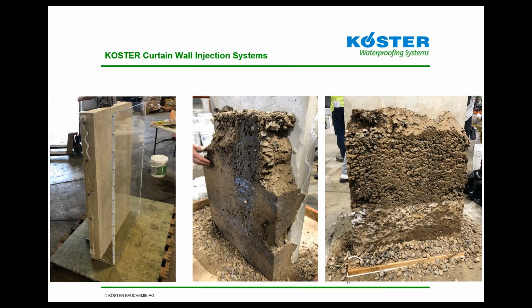As an example, here's a mock-up that we did. This is one of our standard training demos where we create a wall and just backfill with normal soil, then inject through the wall to show the performance of the materials. The center picture there is the KOSTER G4 that we injected through the standard injection ports at 12-inch spacing into that substrate. The picture on the right is the KOSTER S4, which has that shorter reaction time. So you can see, instead of maybe penetrating all the way back through the wall, it reacted much more quickly and formed its barrier a little bit closer to the back side of the substrate.